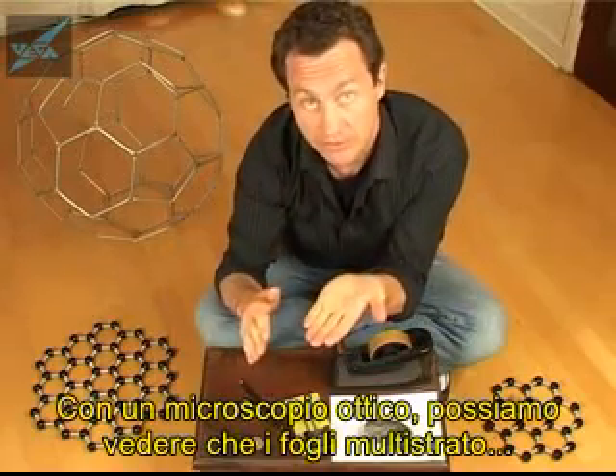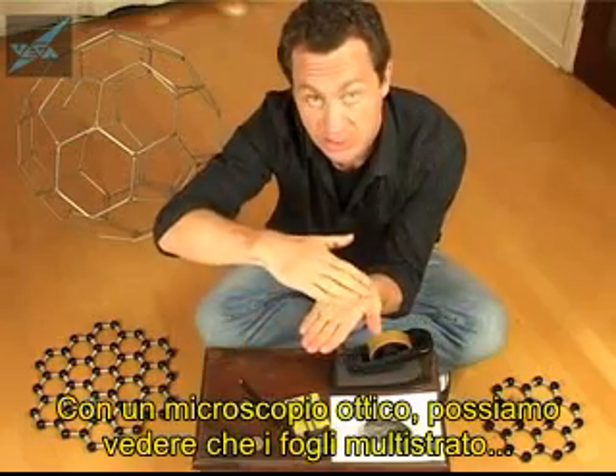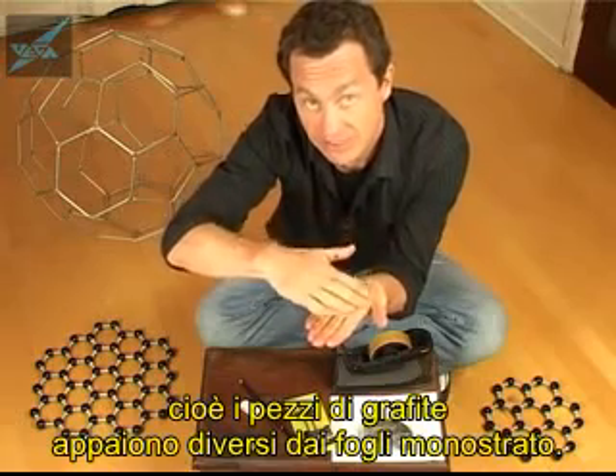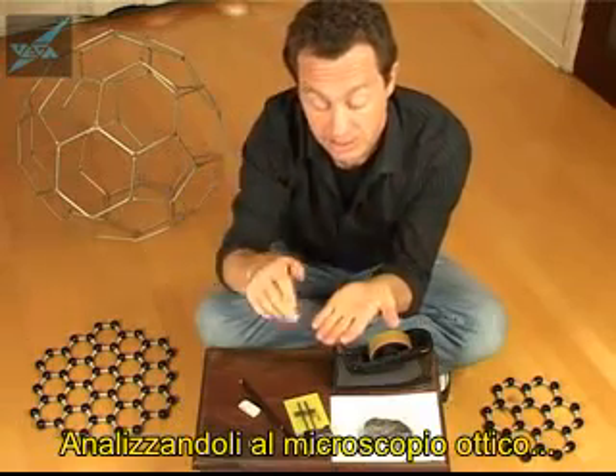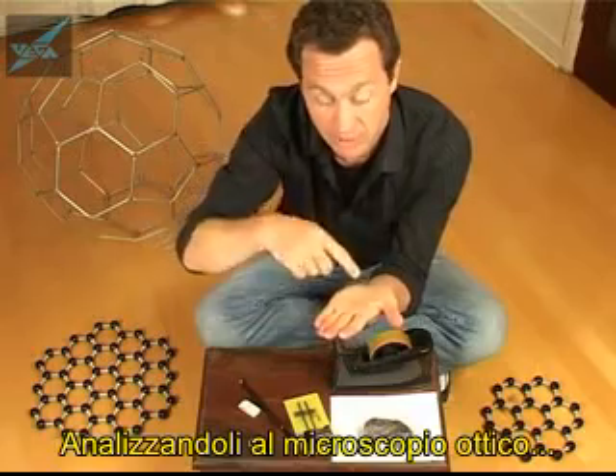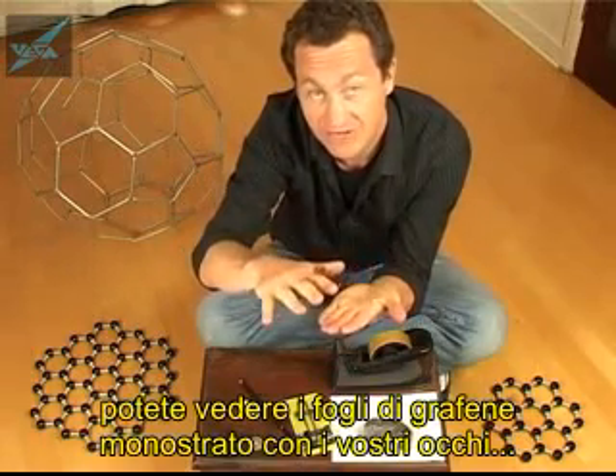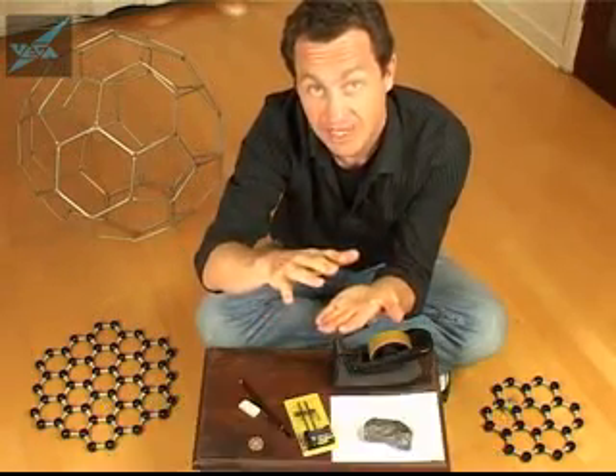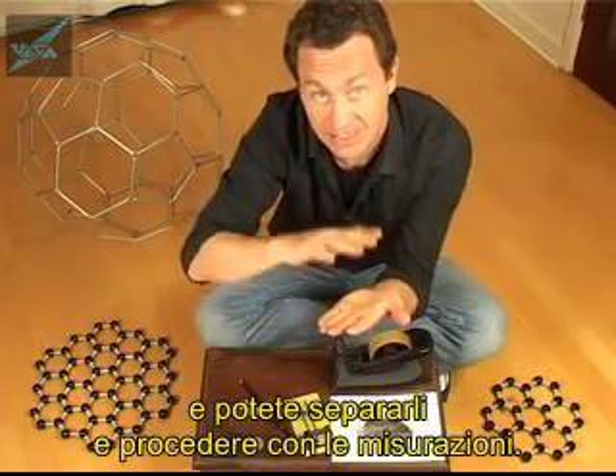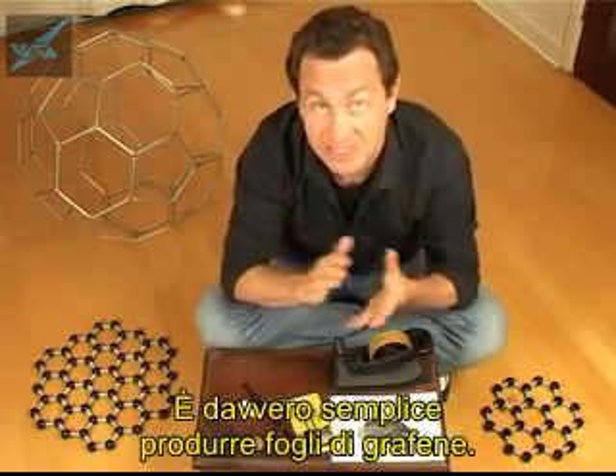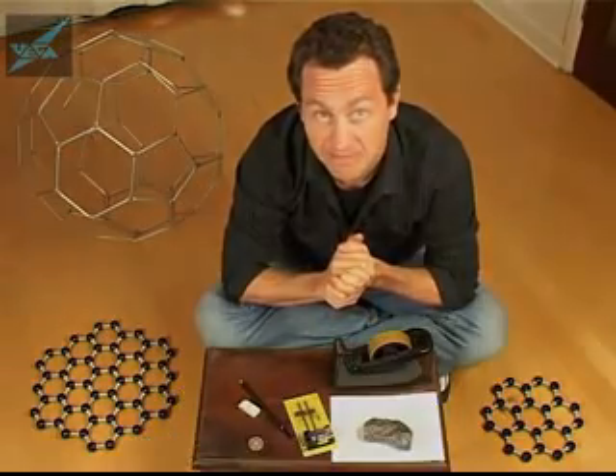And with an optical microscope, it turns out that the multi-layer sheets, the pieces of graphite, look different from the single layer sheets. And so just by inspecting it with an optical microscope, you can actually see the single layer graphene layers with your eye. And then you can obviously separate them out and start doing measurements. So it's incredibly simple to make a graphene sheet.